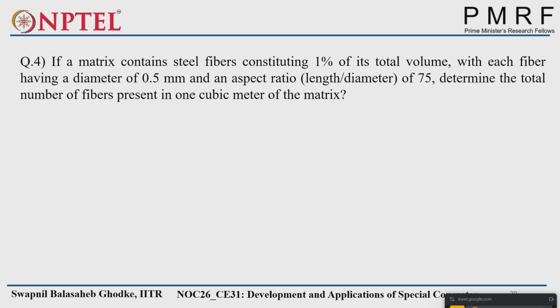Next, if a matrix contains steel fibers constituting 1% of its total volume, with each fiber having a diameter of 0.5 mm and an aspect ratio, length to diameter, of 75, determine the total number of fibers present in 1 cubic meter of the matrix. Calculate this one.